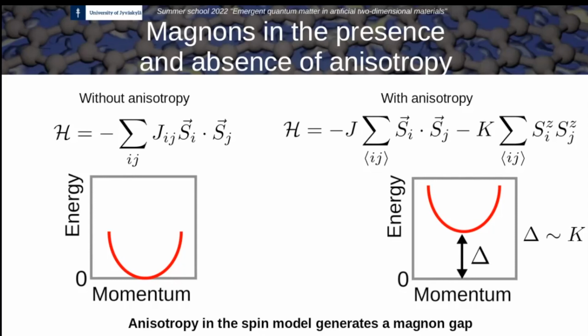So let me rephrase that statement. Of course, in any material you are going to have a term like this, and this term may promote out-of-plane magnetism or in-plane magnetism. If it is bigger than zero, it promotes out-of-plane magnetism. If it is smaller than zero, it promotes in-plane magnetism. And this is just a statement about the sign. Positive sign, out-of-plane; negative sign, in-plane. Now, if you have positive sign and you are out-of-plane, then the magnitude of this term determines your critical temperature. So for positive sign, the magnitude matters. For negative sign, the magnitude doesn't matter, because what stabilizes magnetism is now dipolar interactions. So I think that's the right way of phrasing it. Yeah, thanks. That was a very good point.